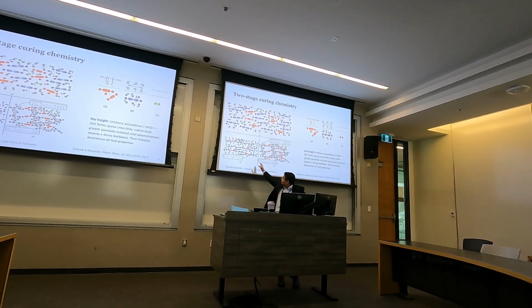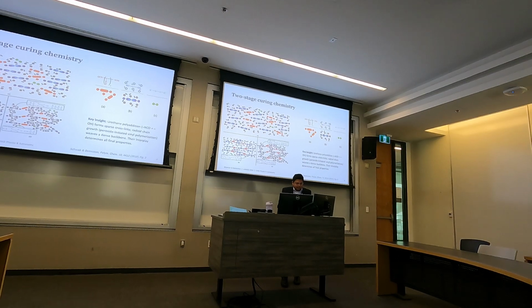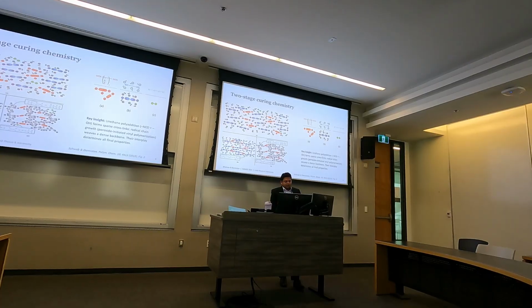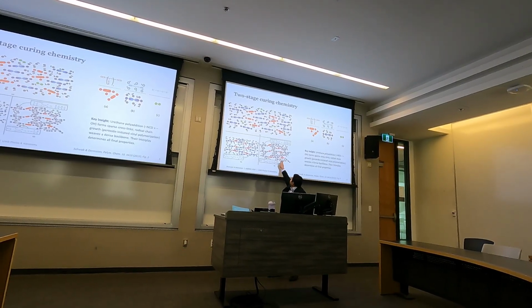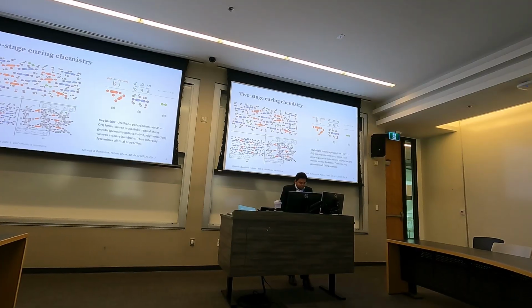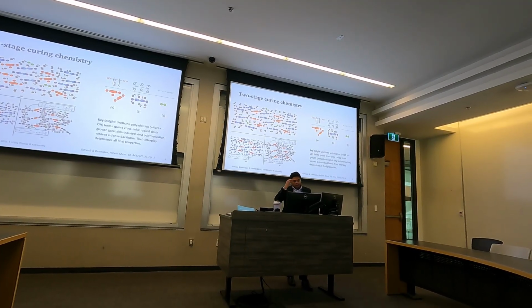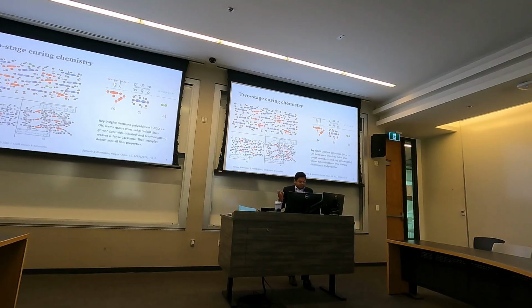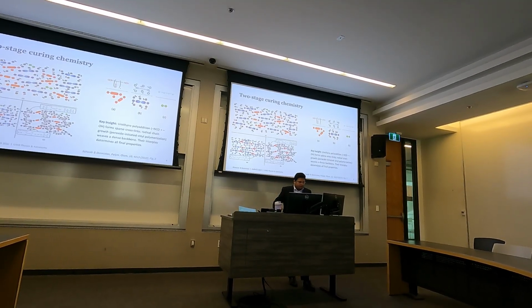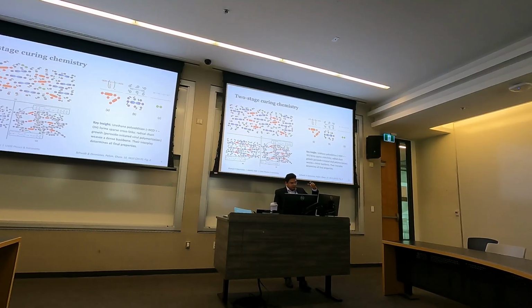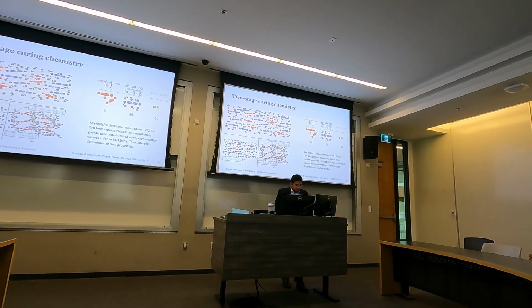Panel C is the fully cured state after the radical chain polymerization happened, and that's why you see these chains of polymers. This is because the peroxide initiator decomposes into radicals that ultimately attack the vinyl double bonds, weaving a dense cross-linked network.